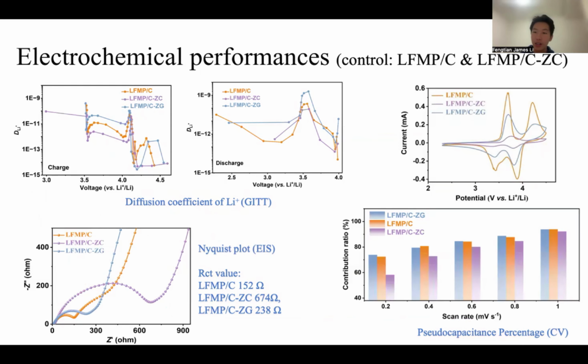And from all of the other electrochemical tests we did, it is mostly for the conductivity and surface chemistry. For the diffusion coefficient of GITT, you see the ZG stands at the top, so it has the best lithium transport property. For the EIS, we can see, although there is an extra layer wrapped on the LFMPC, that the internal resistance is not that bad, right? And the pseudo-capacitance percentage from the CV basically means the rate of the Faradaic process, the electrochemical process on the surface. The ZG is also standing at the top.